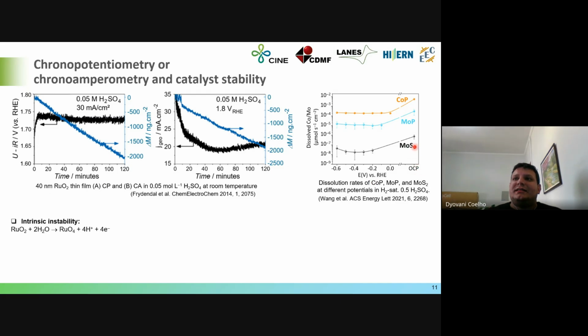So here, the catalyst is negatively polarized, and even though the catalyst shows some dissolution during operation, the dissolution in OCP, in open circuit potential, is at least one order of magnitude higher than the dissolution during operation. So this is important. This is really important, because sometimes the industrial device is just stopped for maintenance and things like that. So it is important to know what happens with the catalyst when the system is just shut down.